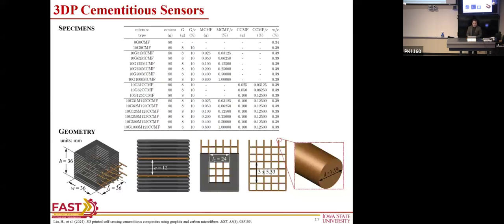Just look here at the geometry that we have. So we try to keep those mesh constants. What we measure is the strain between both meshes. We connect to both, and that's your resistor. You measure resistance, and that resistance will change as a function of strain, and hopefully you achieve some good sensitivity.